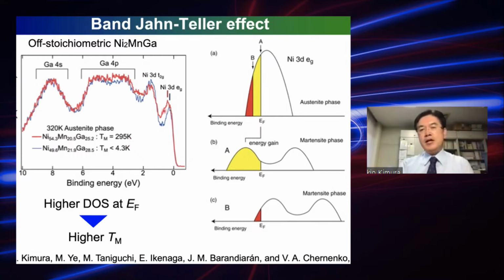As you can see, a much higher density of states at the Fermi energy is observed for the sample with a higher Martensitic phase transition temperature. And of course, the other sample with a lower Martensitic phase transition temperature shows a smaller density of states. This result tells us that when you have the Fermi energy just near the peak of the density of states, actually in the minority spin channel, you can cause the instability of the cubic phase, because a large energy gain can be expected when you have the Fermi energy near the peak of the density of states.